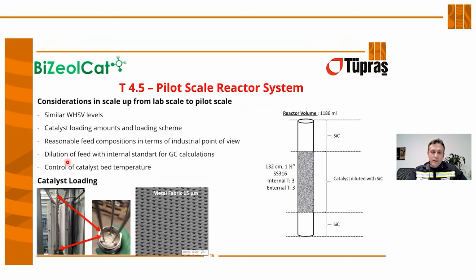Now, how we load the reactor. This reactor system allows us to use reactor tubes of different diameters, starting from 1/2 inch, 1 inch, and 1.5 inch. We used a 1.5 inch reactor diameter in both the propane dehydrogenation and propane aromatization reactions.